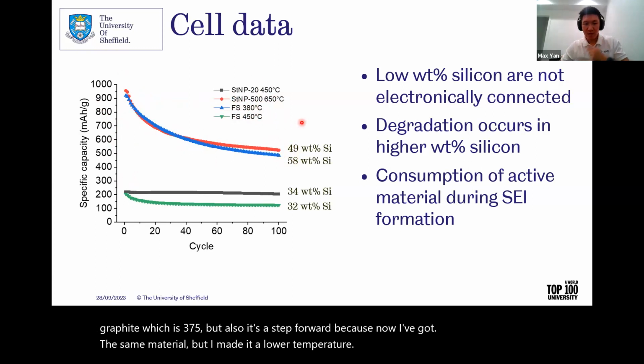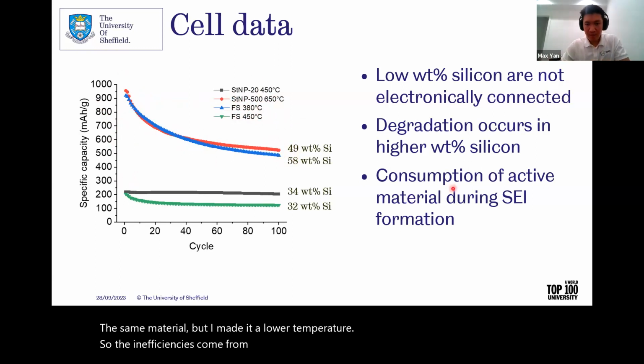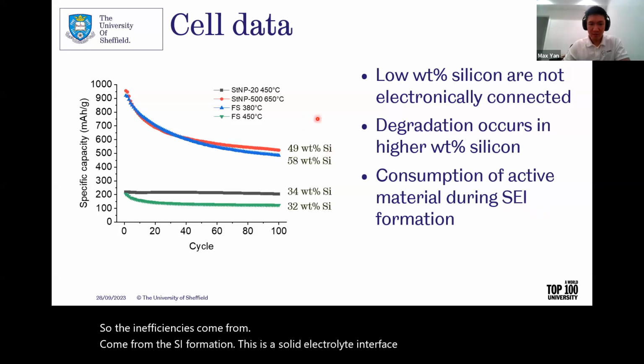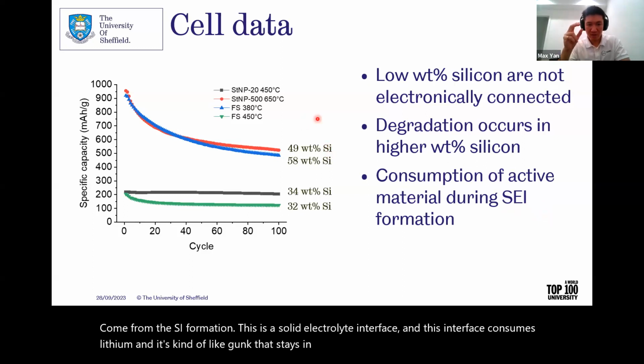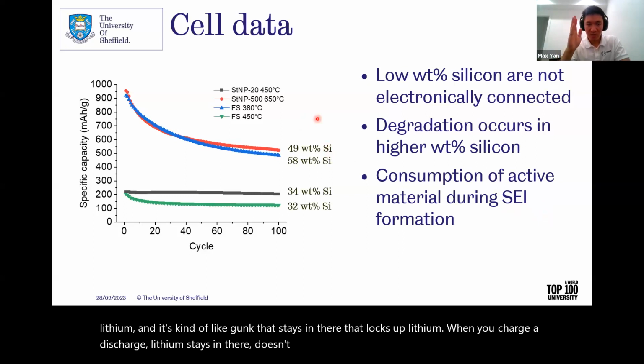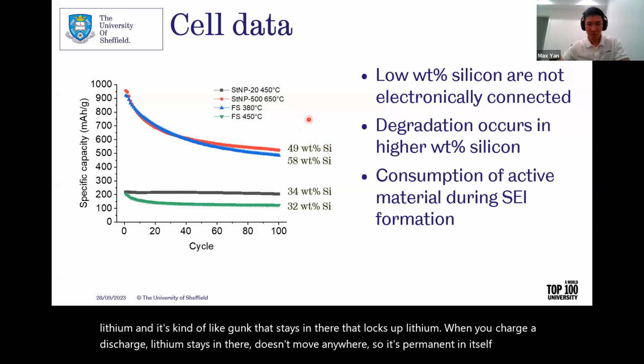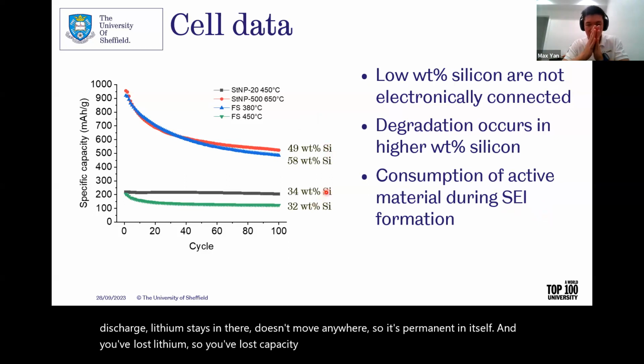So the inefficiencies come from the SEI formation. This is solid electrolyte interface. And this interface consumes lithium, and it's kind of like gunk that stays in there that locks up lithium. When you charge or discharge, the lithium stays in there, doesn't move anywhere, so it's permanent in the cell, and you've lost lithium, so you've lost capacity. And this electrolyte interface grows and grows.